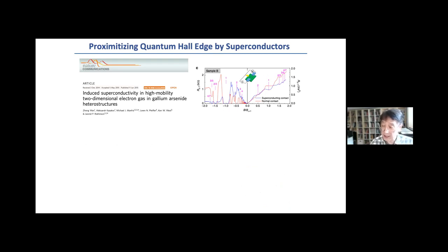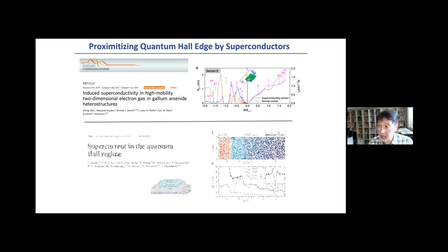While this gave us an intriguing result, as shown here, making reliable contact between niobium and a semiconductor was not easy. Part of the reason is that you have to really fight the Schottky barriers, especially from a refractory metal like niobium, and making reliable contact with semiconducting material has been one of the big technical challenges. Of course, as I said, graphene has an advantage because in principle there is no semiconductor gap. Therefore, you can make decent contact with many different materials, including niobium or molybdenum, those type 2 materials with reasonably high Hc2.